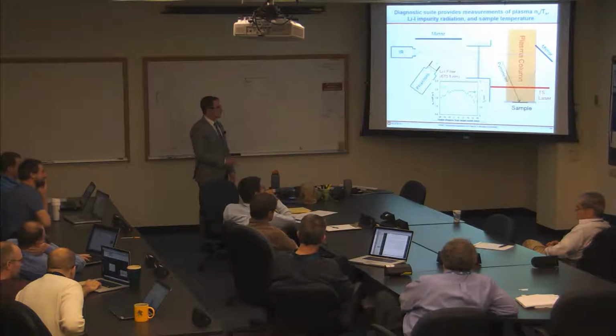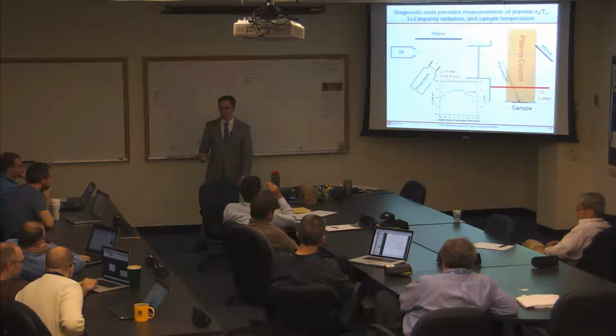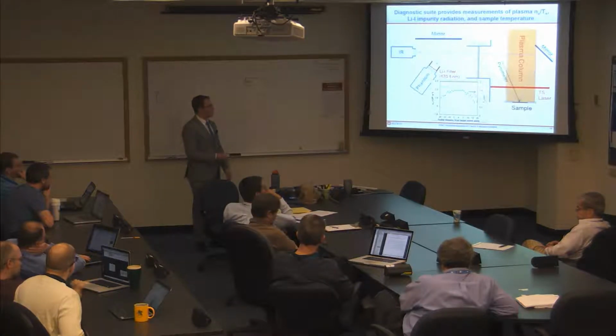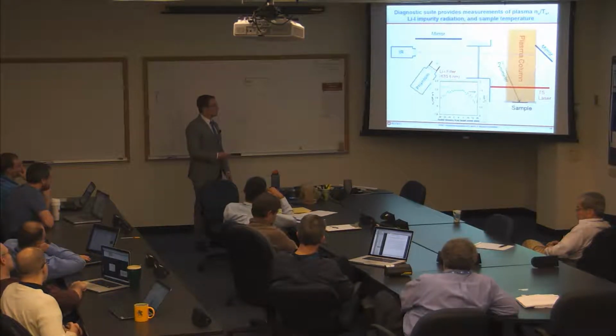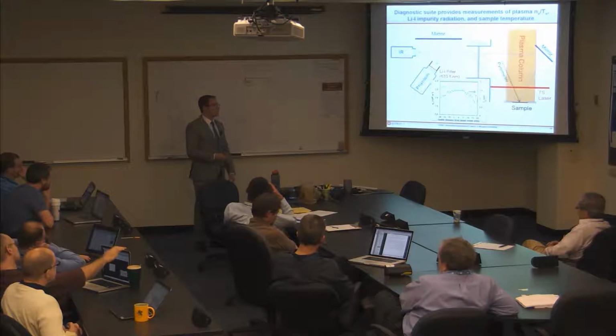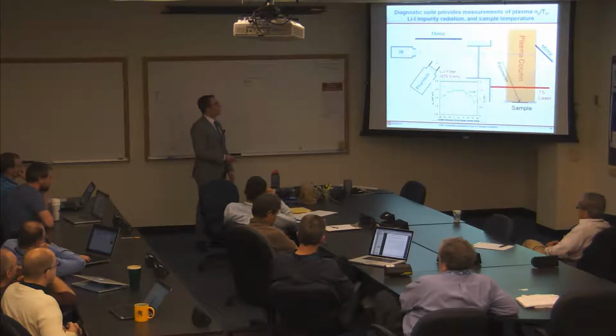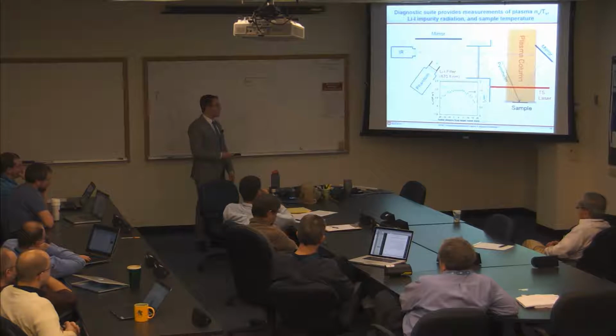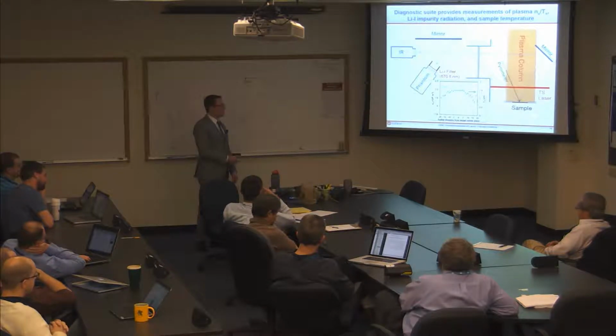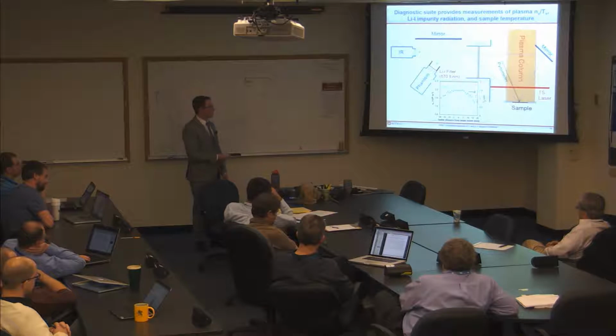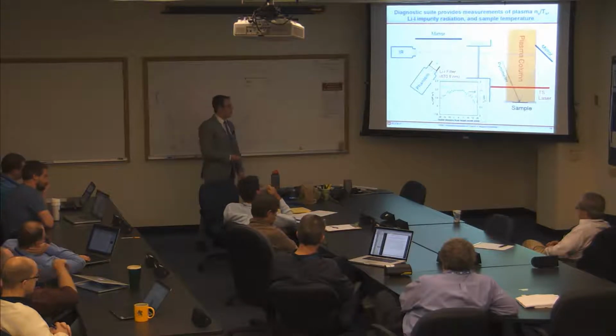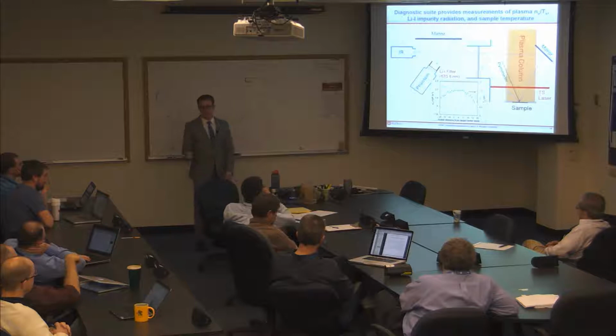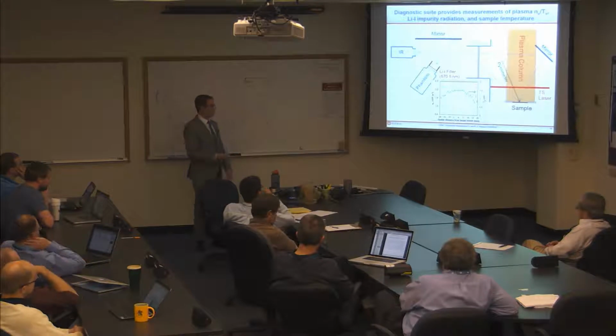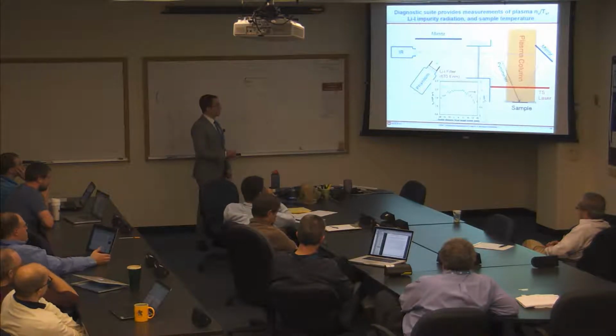There was also this spectropyrometer, which is essentially an infrared spectrometer. So it measures all of the light in the infrared range from about 1.2 to 1.8 microns. And what you can do is you can fit a gray body Planck's law equation to the pyrometer data to get an emissivity independent measure of the sample temperature, which is useful because it's expected that the lithium emissivity is actually a pretty strong function of temperature.